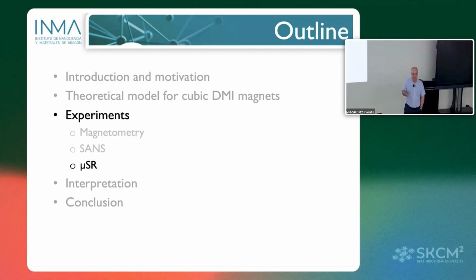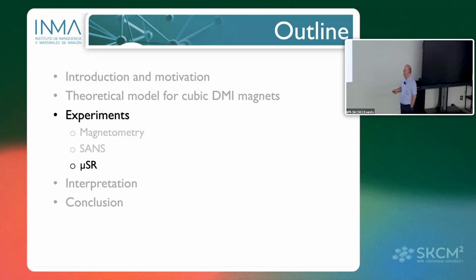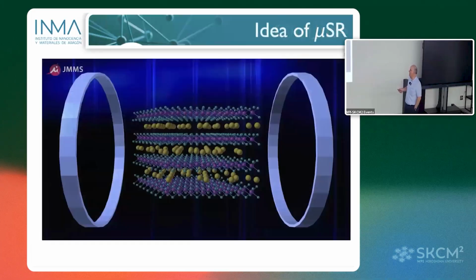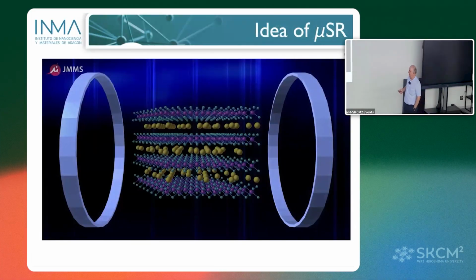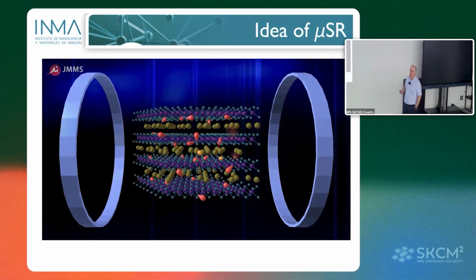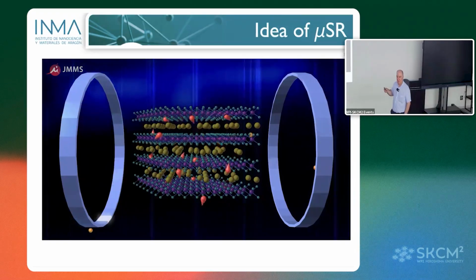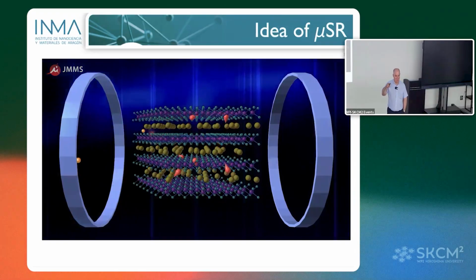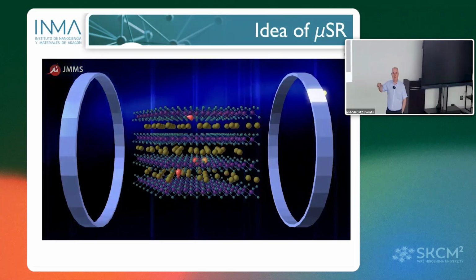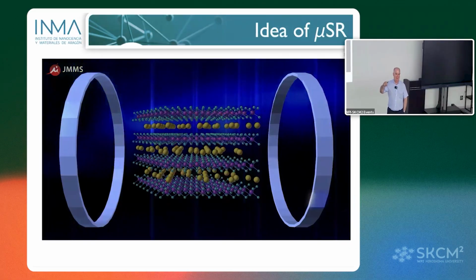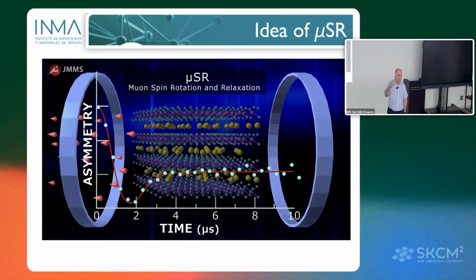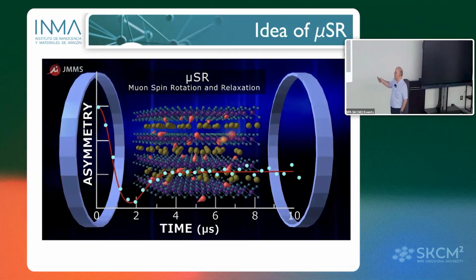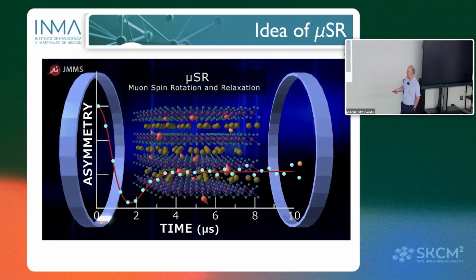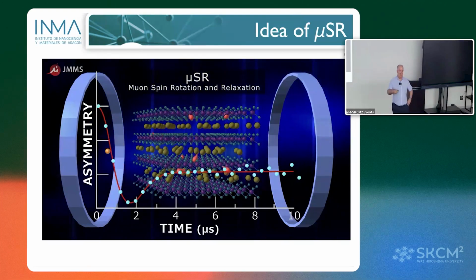But you will see in the discussion what kind of helices. Then let's go to do muon spin rotation experiments. I don't know if you are familiar with muon spin rotation. With muon spin rotation, you implant muons in your material. The muon is, in this case, a positive muon. The muon will go to sit in a given point in your material in which the charge is favorable. That means minimum negative charge because the muon is positive. And then after a few microseconds, the muon will decay.